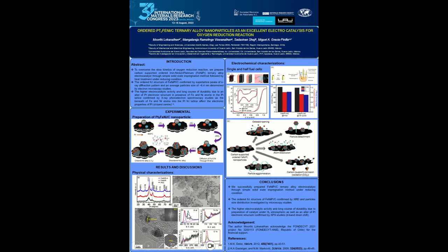This is due to hybridization, meaning Fe and nickel 3d to Pt 5d hybridization. In that case, what will happen? It will increase the Pt electronic 5d vacancy, so it influences the Pt electronic structure. The increment of the 5d vacancy is highly boosting the oxygen reduction reaction.